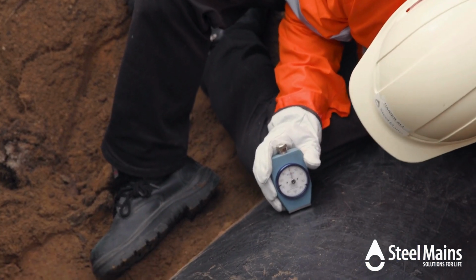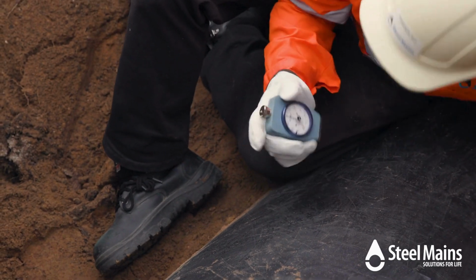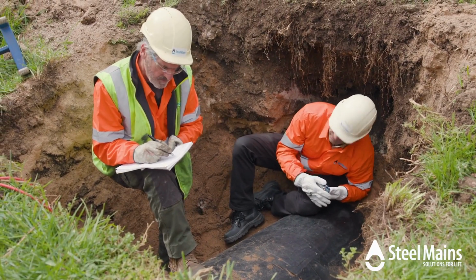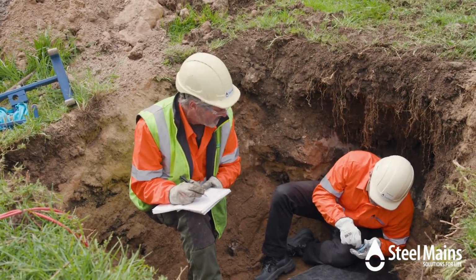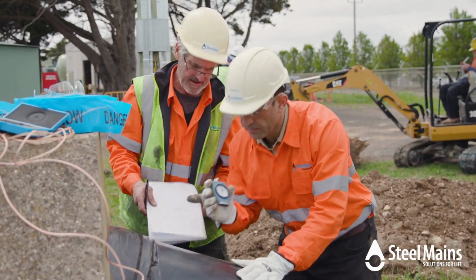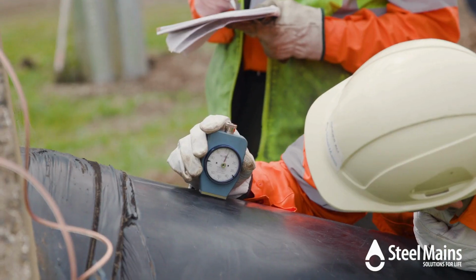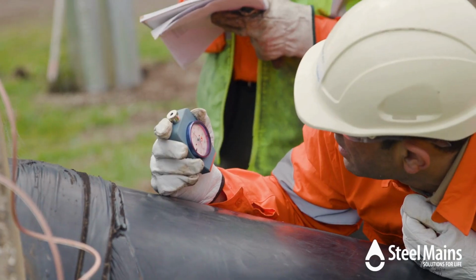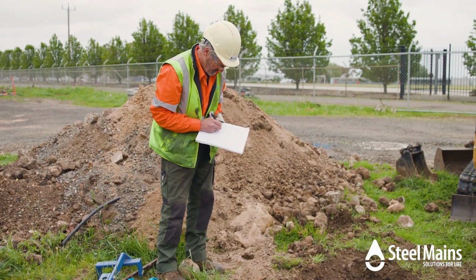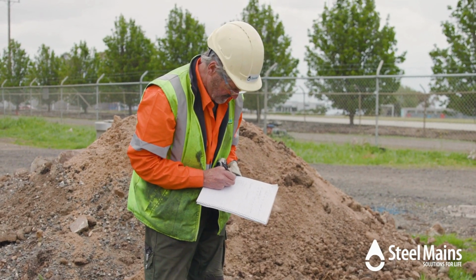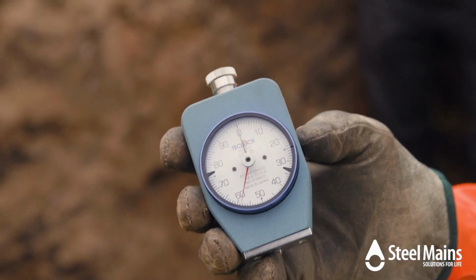A hardness gauge is placed on the exhumed pipe. The result? 58 Shore D. The comparable reading from the above ground section measures slightly less, 57 Shore D, well within an acceptable margin of error. These results confirm that after 48 years in service, the coating hardness remains stable and unaffected.